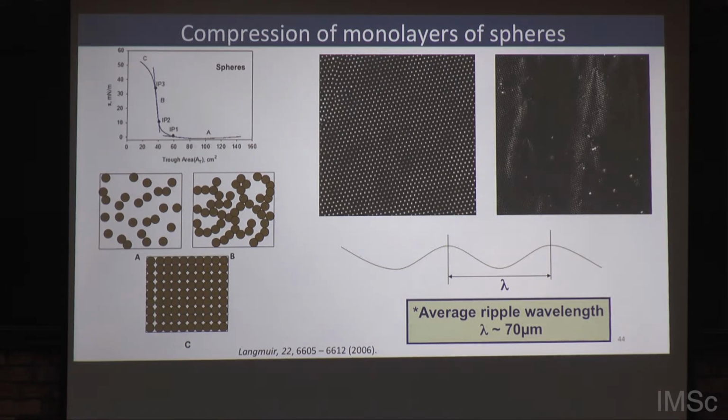because we have done these experiments. Let me explain the experiment. You take water in a container, you put a small amount of alcohol on the surface, you put a Wilhelmy trough and you start measuring the surface tension. You will see that the surface tension between water and air, which is 72 millinewtons per meter, starts decreasing, and this decrease happens until a certain time. It's a hydrophobic collapse. So that's why we are saying that,